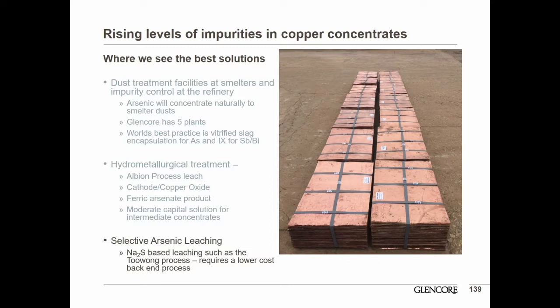The other technology that Glencore had developed internally is a sodium sulphide-based leaching process named the Toowong process. That's one that we're currently continuing to look at with a partner, Core Resources. This is a technology where we can actually generate the sodium sulphide in situ within the leaching circuit rather than have to add sodium sulphide from an external source. It's an emerging technology that we think in the next 10 years can have a significant impact in trying to selectively remove arsenic out of copper concentrates as well.